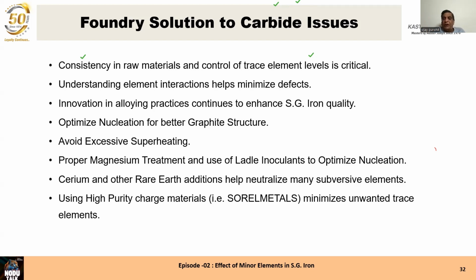We cannot afford to have channels in our spectrometer for detecting the subversive elements, and we cannot get the standards to calibrate the channel to know exactly how much amount of these subversive elements are present in our charge mix or a liquid metal. Therefore, please make sure that you use rare earth containing ferrosilicon magnesium, and make sure your cerium is not very high in heavy section castings.